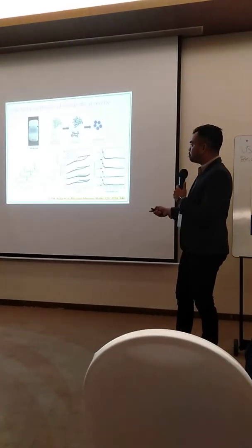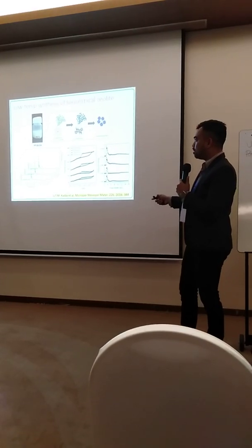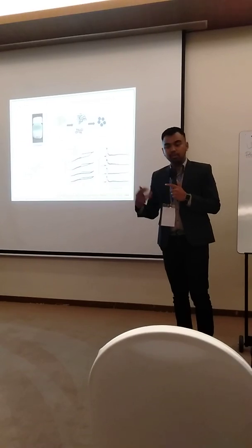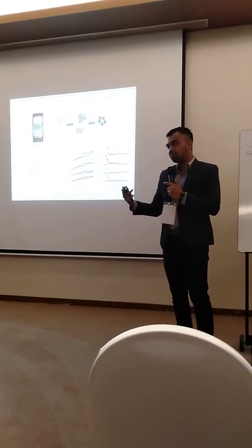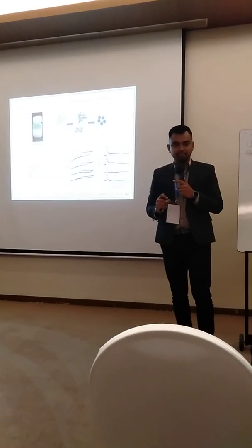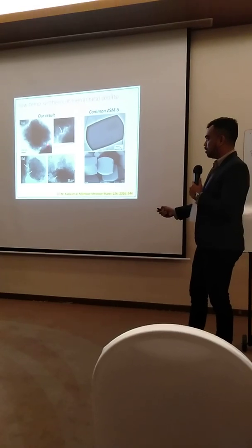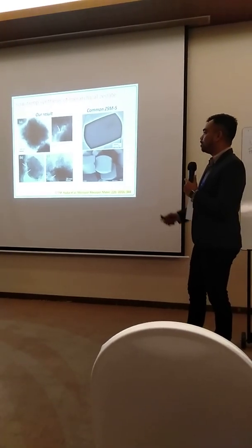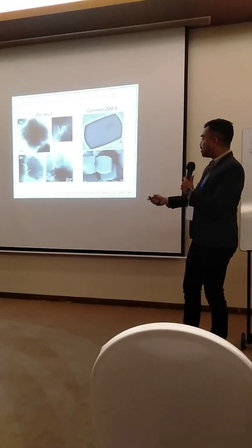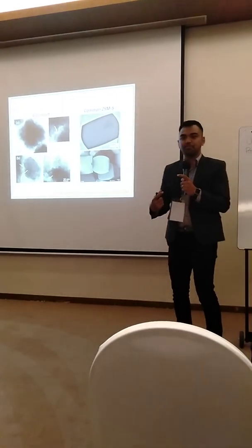So as you can see, if we lower the temperature, there will be formation of numerous nuclei. Numerous nuclei will result in small crystallites. These small crystallites will aggregate to form aggregation of small particles, which gives mesopores. So we can